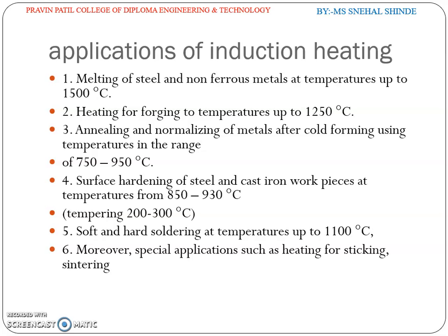annealing and normalizing of metals after cold forming using temperatures in the range of 750 to 950 degrees Celsius, surface hardening of steel and cast iron workpieces at temperature from 850 to 930 degrees Celsius. Tempering is 200 to 300 degrees Celsius. Soft and hard soldering at temperature up to 1100 degrees Celsius. Moreover, special applications such as heating for sticking and sintering.